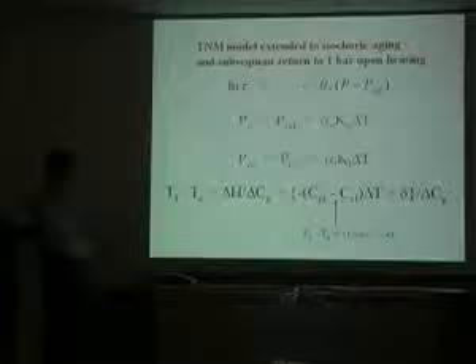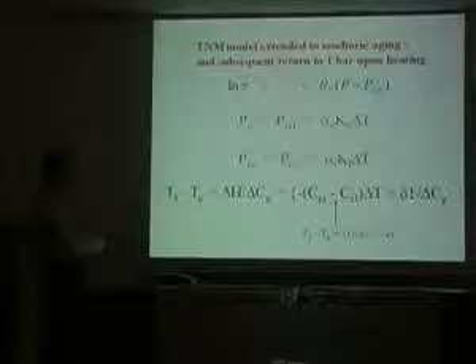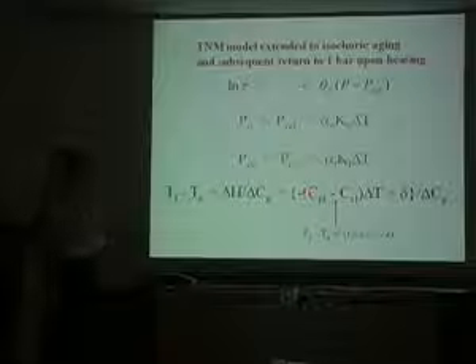It's delta H over delta CP. And then we have the CPL minus CPG term, delta T plus delta over delta CP. And this is the reason why TF minus TA does not go to 0, as I showed on the schematic, as the departure from equilibrium goes to 0.